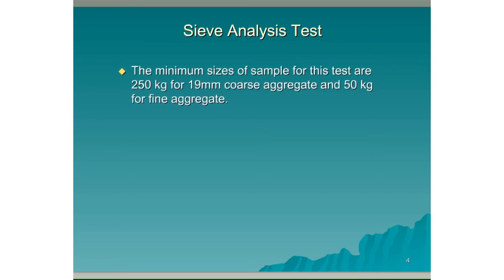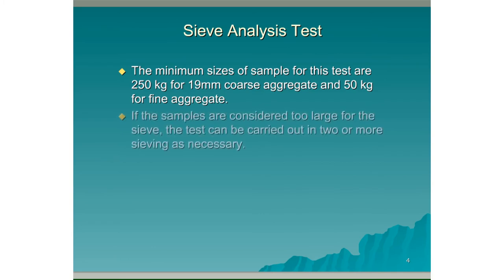The minimum sizes of sample for this test are 250kg for 19mm coarse aggregate and 50kg for fine aggregate. If the samples are considered too large for the sieve, the test can be carried out in two or more sievings as necessary.